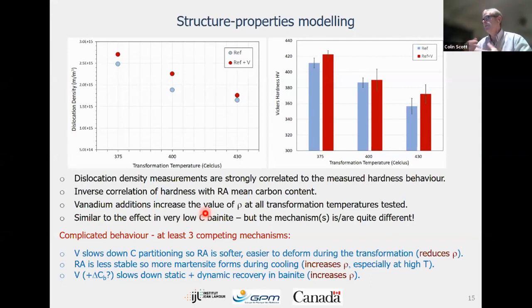So during the transformation, it's easier to deform, and that should reduce the overall dislocation density. At the same time, that retained austenite is slightly less stable, so you get more martensite forming during the cooling part, that will increase the dislocation density, especially at higher temperatures. It won't have a big effect at low transformation temperatures.